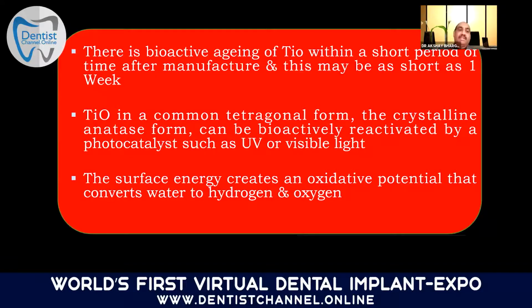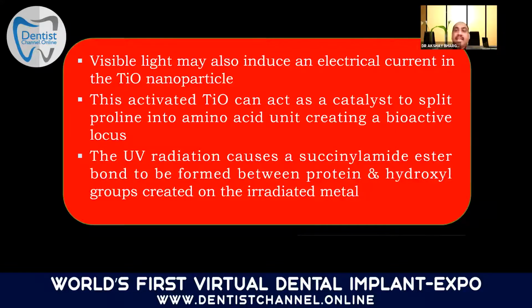osseointegration potential is concerned. Titanium oxide in a common tetragonal form, the crystalline anatase, can be bioactively reactivated by a photocatalyst such as UV or visible light. The surface energy creates an oxidative potential that converts water to hydrogen and oxygen. Visible light may induce an electric current in the titanium nanoparticle. This activated titanium oxide can act as a catalyst to split the proline and amino acid units, creating a bioactive locus. Basically, radiation causes a succinyl amide ester bond to be formed between a protein and hydroxyl.